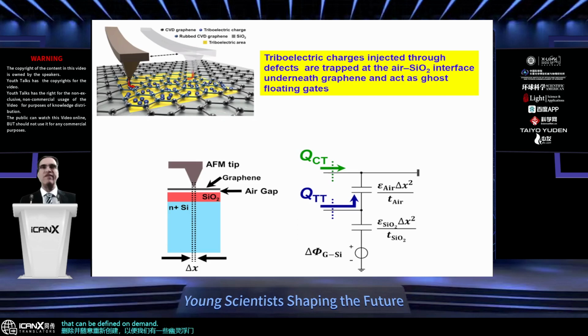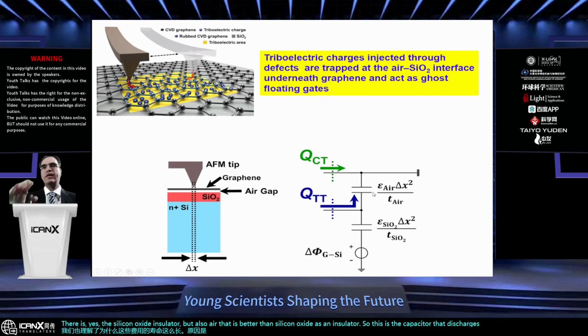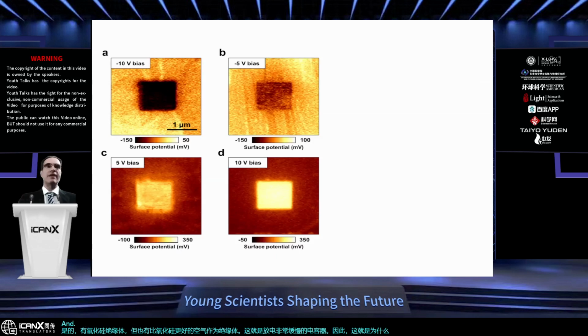So unlike the conventional material gates that are fabricated once forever, these gates can be created, deleted, recreated, modified. One can modify the area and so on. So with this model that you see here, we also understood why the lifetime of these charges was so long. The reason is that there is, yes, the silicon oxide insulator, but also air that is better than silicon oxide as the insulator. So this is a capacitor that discharges very slowly, and that's why the lifetime is so long. And here are some additional experiments.